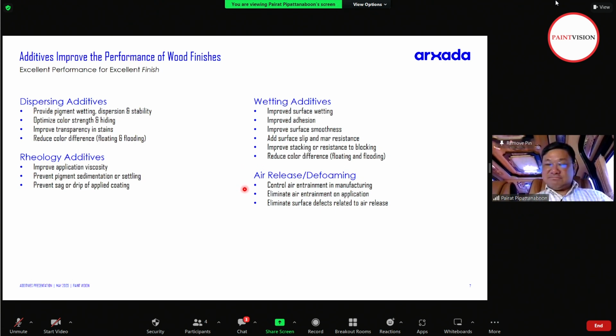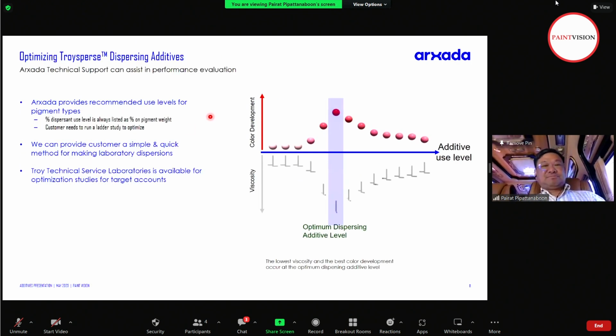Air releasing system or defoamer helps to control air entrainment during manufacturing of your paints. It also eliminates the air bubbles during application. Of course, you make the surface smooth so you get the gloss you wish. Rheology additive helps to control anti-sagging and anti-settling, especially if you use fumed silica as matting agent in your system. It also improves the application viscosity, the low shear and high shear concept.